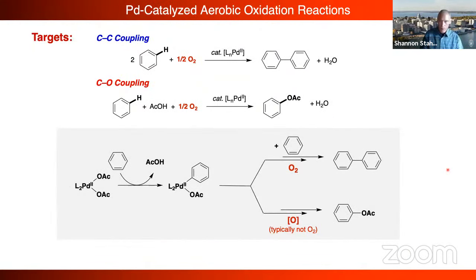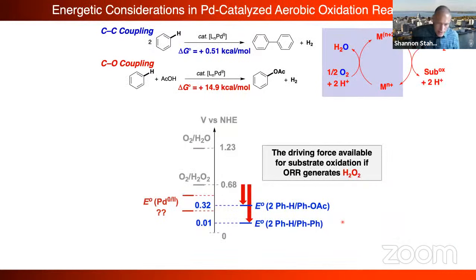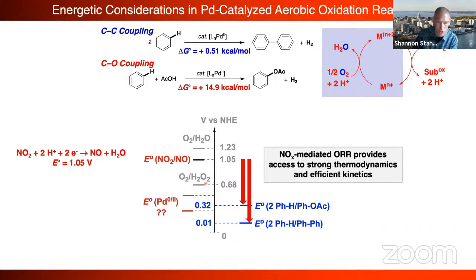Okay. I want to end by just coming back to this palladium reaction, because again, O2 does not make phenylacetate. And the question is, can we change that? Well, I've just shown you a possible strategy. What we started with was by looking at palladium and O2, we often make hydrogen peroxide. So we don't have much driving force available from O2. Well, let's use NOx. NOx as a redox couple will give us a much greater driving force.